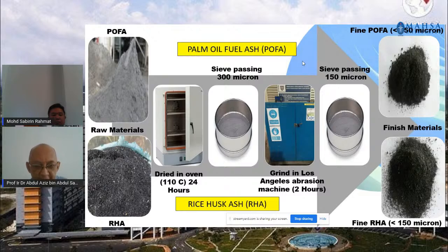So this is the first level of the material preparation for the palm oil fuel ash and the rice-husk ash, where we try to get the size of the material for POFA and rice-husk ash at approximately 150 microns.